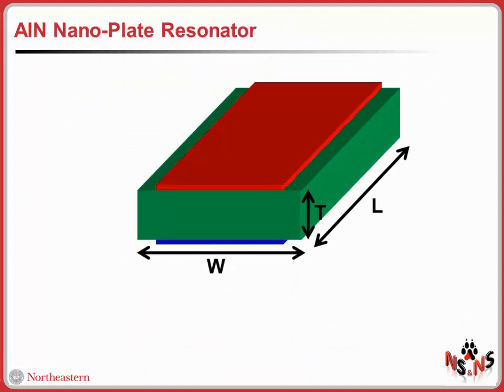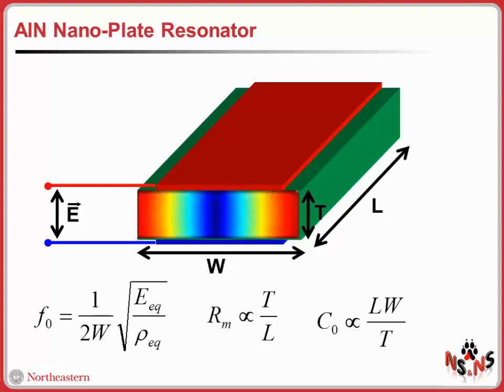So these are nanomechanical resonators. It's composed of an aluminum nitride thin film sandwiched between two metal electrodes. When an electric field is applied across the thickness of the piezoelectric layer, a contour extension mechanical mode of vibration is excited through the D31 equivalent piezoelectric coefficient of this aluminum nitride. So the operating frequency of this laterally vibrating structure is set by the width of the plate, while the two other geometrical dimensions are substantially used to set the equivalent electrical impedance of the device.